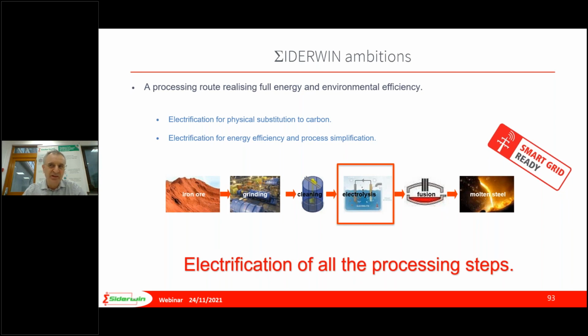Siderwin also capitalizes on this operative temperature, which is low, 110 degrees, compared to conventional processes that are operated at 1000 degrees. In order to be flexible, we have a system where we are not limited by problems of passivation, because our system depassivates, it breaks down the oxides. So today we have good laboratory results showing that we have a good potential to propose a big industrial process that is flexible.